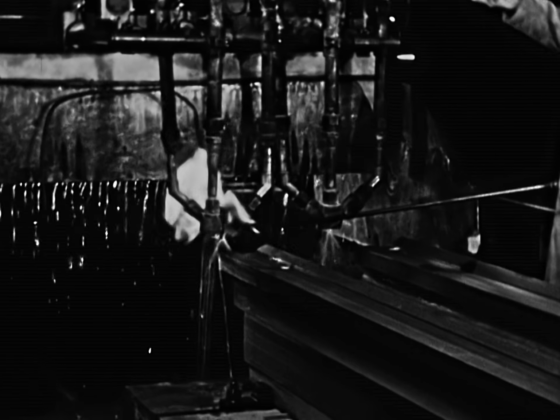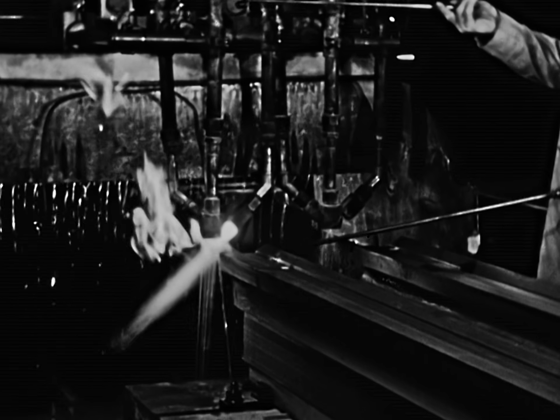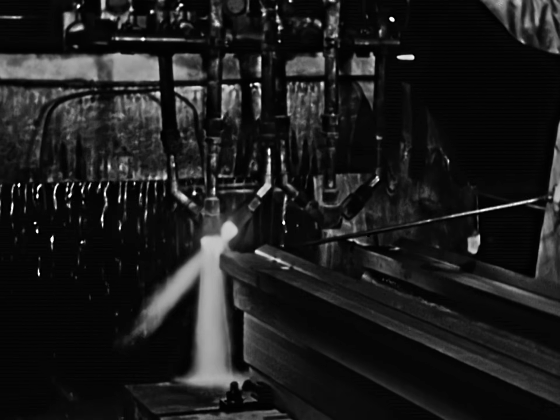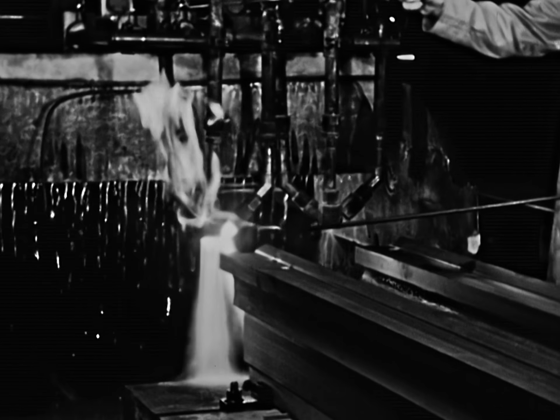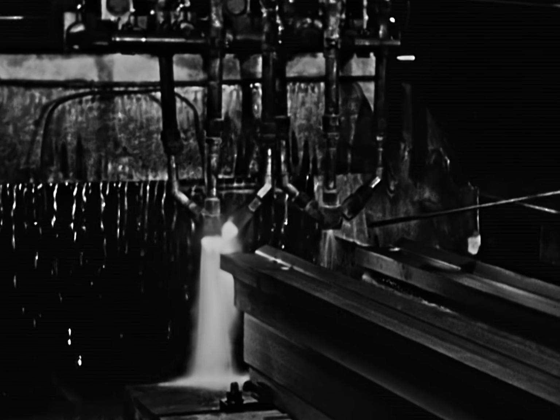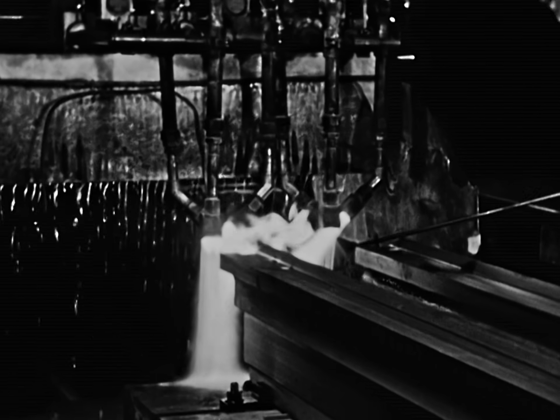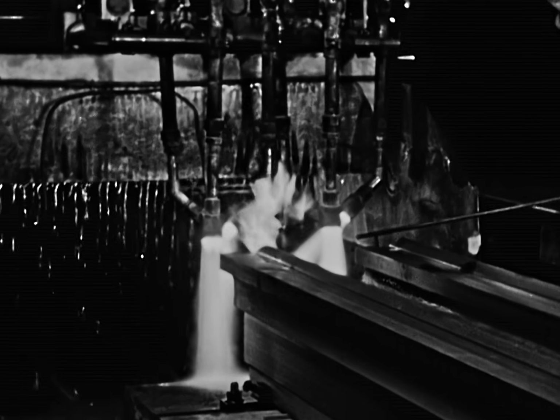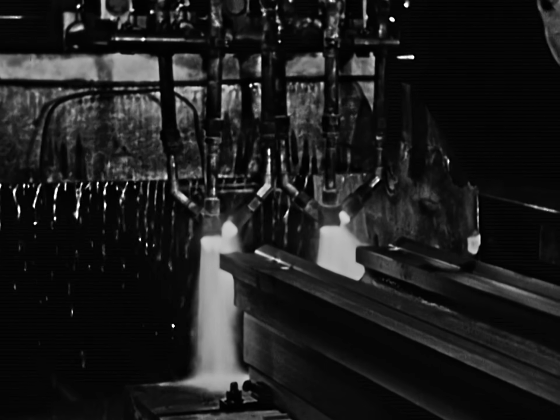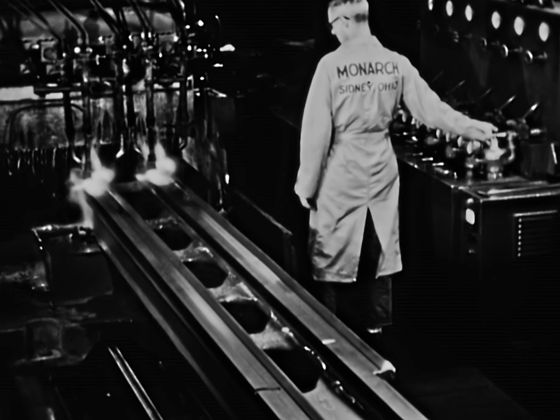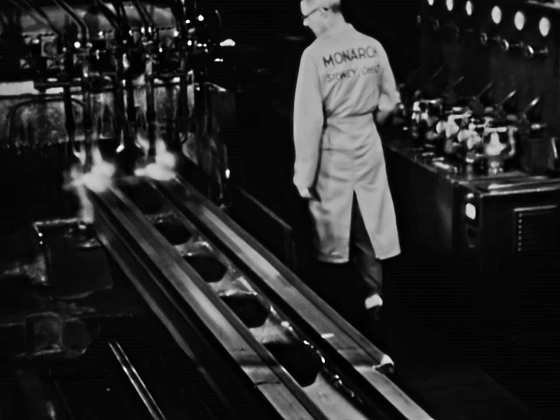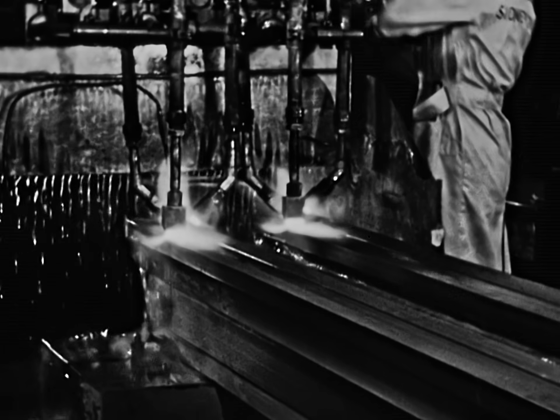This is how Monarch flame hardens its bedways. Developed back in 1936, flame hardening assures lifelong bedway accuracy to the users of over 25,000 Monarch lathes. Both flat and V surfaces are hardened simultaneously to the depth of 1/8 inch plus, and with a Shore scleroscope reading of 70 to 72.